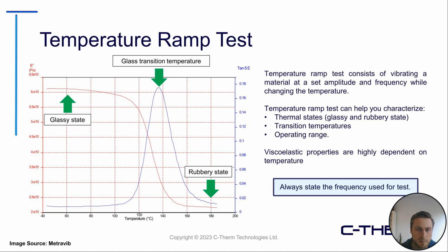As we can see here from the plot on the left, the material transitions from a glassy state at 40 degrees Celsius to a rubbery state near 180 degrees Celsius, showing these viscoelastic properties are highly dependent on temperature. I'll say here, I'm kind of a culprit of this.